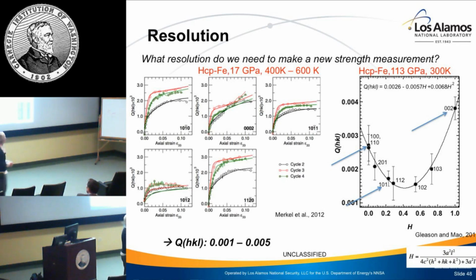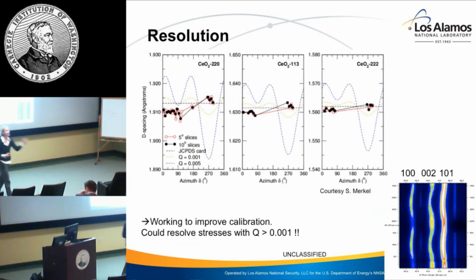The answer is yes, okay? I can resolve stresses in my dynamic compression experiment down to a little above 0.001 Q. In other words, I have the resolution. If iron is really as weak as I predict it to be, 1 to 2 GPa, at inner core conditions, I should be able to resolve it with in situ dynamic compression, high pressure, high temperature experiments.